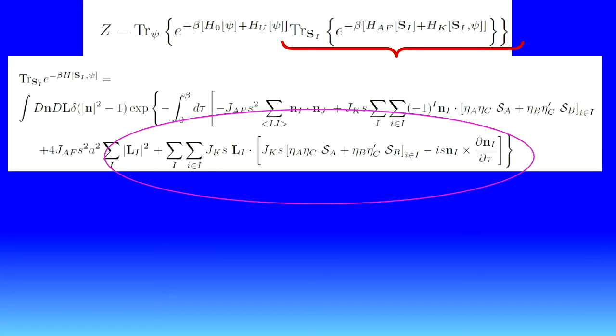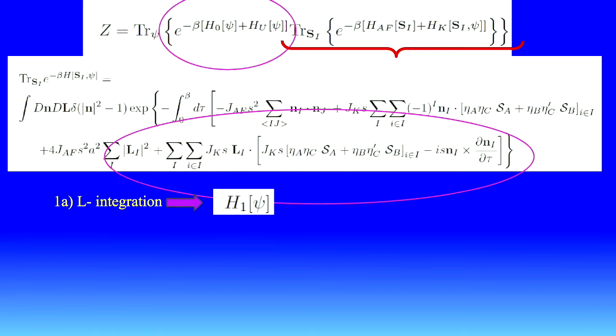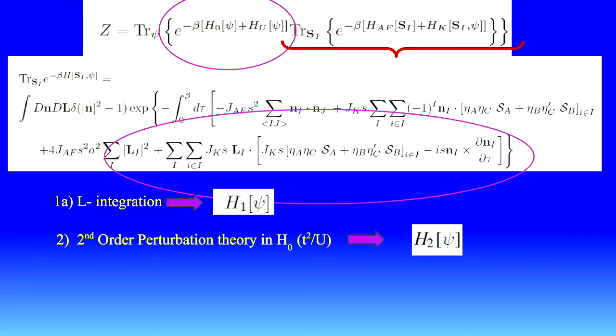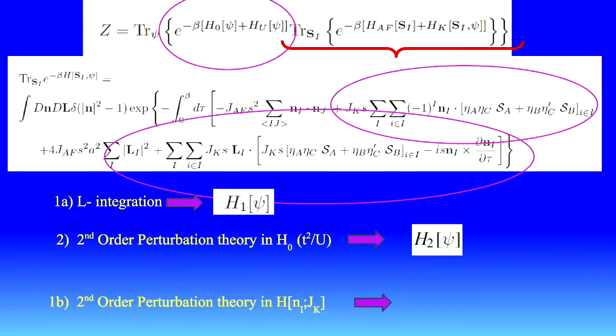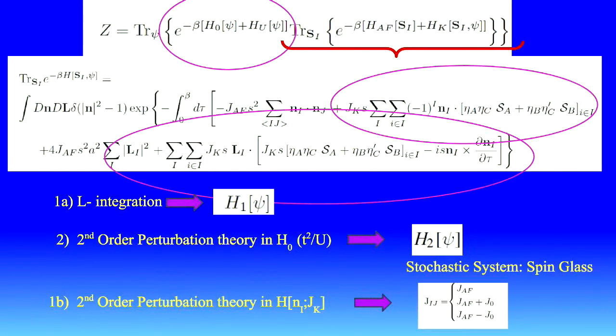The integral is a quadratic one. You have a quadratic and a linear term. If we integrate in L, we will obtain one Hamiltonian, H1. If we do second order perturbation theory here, we will obtain a second Hamiltonian, H2. And finally, if I take this term here, which is the magnetic interaction between the itinerant spins and the localized antiferromagnetic component, we get a stochastic system with Heisenberg-like couplings, given by this, with such probabilities.